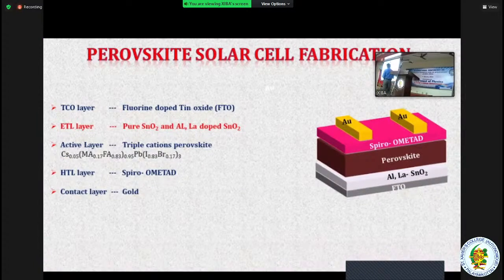Here, the TCO layer is FTO, fluorine tin oxide, and the ETL layer is pure tin oxide, and aluminum and lanthanum separately doped tin oxide. The active layer was the triple cation perovskite. We have not discussed the recipe of this perovskite layer, and the HTL, that is the spiro-OMeTAD layer, so we didn't cover that part also. Then the contact layer was gold. So we changed only the ETL layer: pure tin oxide, aluminum, and lanthanum separately doped.